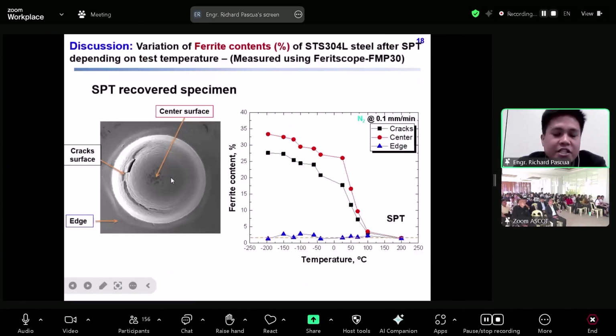Since some studies have shown that this material can undergo phase transformation, particularly at lower temperature, we evaluate the ferrite contents of this material from the deformed and undeformed region at different temperature conditions using the sample tested under nitrogen environment. And when we decrease the temperature, we found out that the ferrite contents continuously increase in the deformed region, showing that there's an induced martensitic transformation occurred in this material during and after deformation. However, in the undeformed region, it showed a constant value, which is almost zero, or there's no variation of ferrite contents, showing that it keeps being austenitic phase at this condition, even though it was exposed to different temperature conditions.